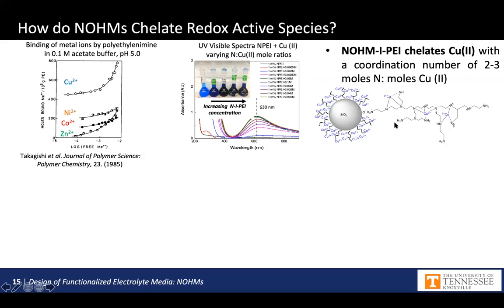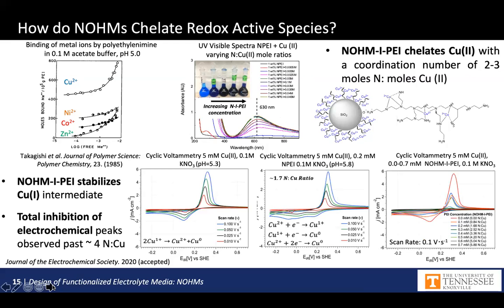So now that we understood how NOHM-I-PEI was chelating copper, we did an electrochemical study, in collaboration with a group at University of Tennessee. And these below are our findings. The first image here is just the electrochemistry of copper in the absence of NOHMs, and we see 2 reversible reduction and oxidation peaks here. And this is the effect that the addition of NOHMs has. There are 2 things to point out that we found.